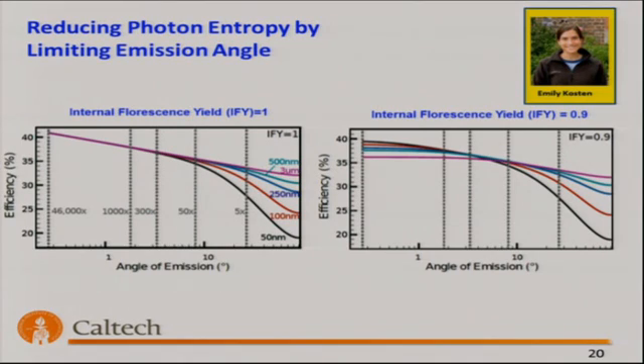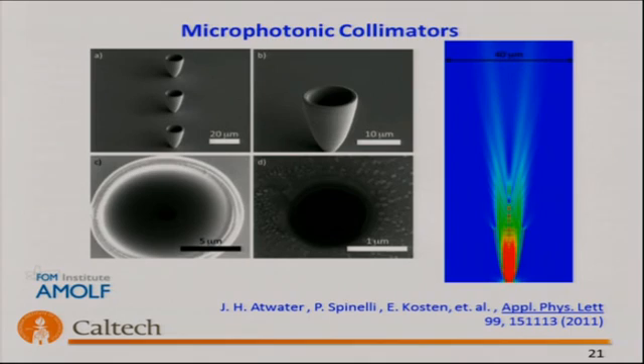So you might ask, well, is this very practical to do? Well, we decided to see if that was possible using microphotonic structures. These are compound parabolic concentrator structures, a curvature that has an optimal curvature for directivity and concentration, and then we produced these structures by 2-photon lithography, drilled a hole in the bottom with FIB, and use these as light directors.